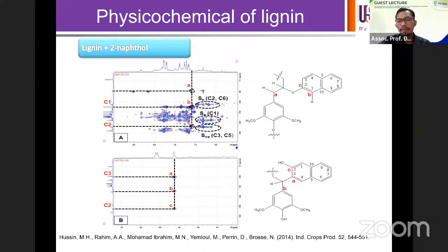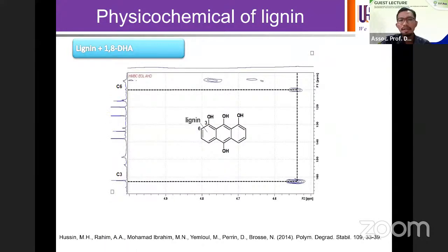And we also performed HMBC, multiple bond 2D NMR, in order to explain where this interaction is located. This experiment gives us some guidance that the modification of lignin can happen especially at carbon 2 or carbon 3 of the naphthalene ring. Meanwhile, for dihydroxyanthraquinone, we noticed from HMBC NMR that it can be proposed that the interaction with lignin could be either at carbon 3 and also carbon 6.